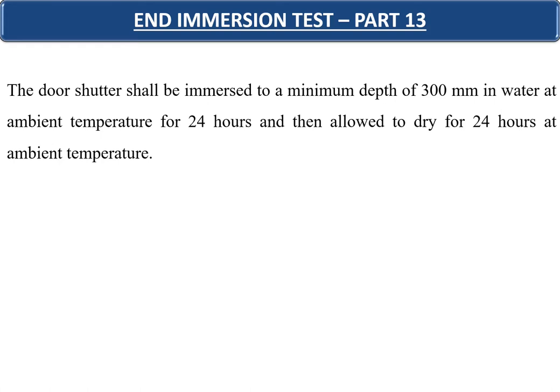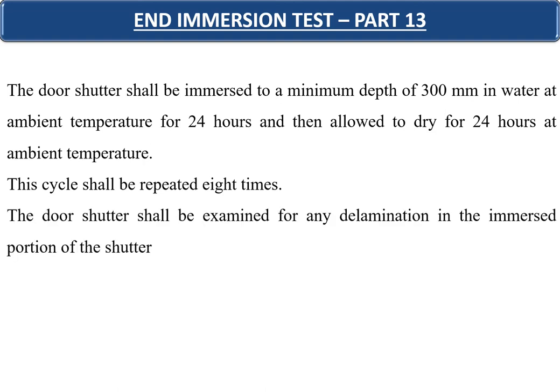Part 13 covers the end immersion test. The door shutters are immersed to a minimum depth of 300 mm in water at ambient temperature for 24 hours, then allowed to dry for 24 hours at ambient temperature. This cycle is repeated eight times. The door shutters are then examined for any delamination in the immersed portion.